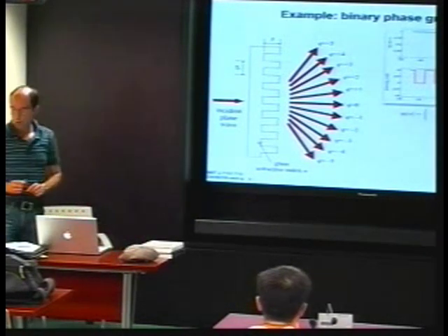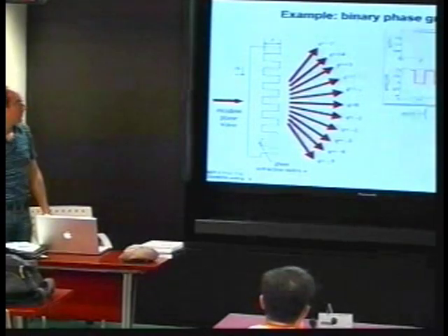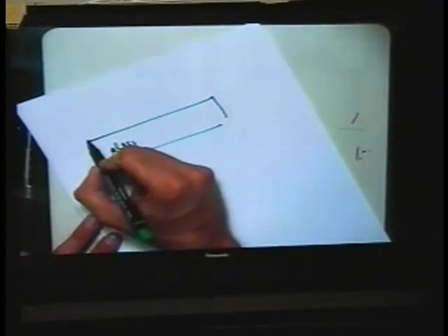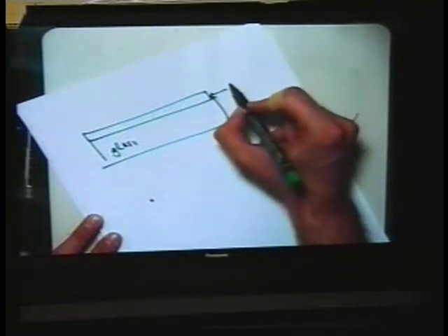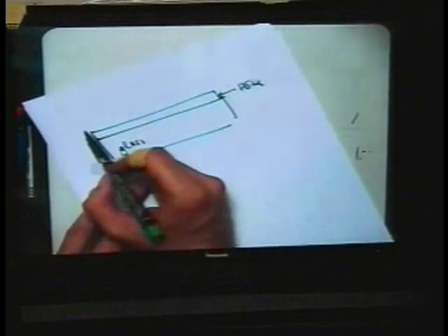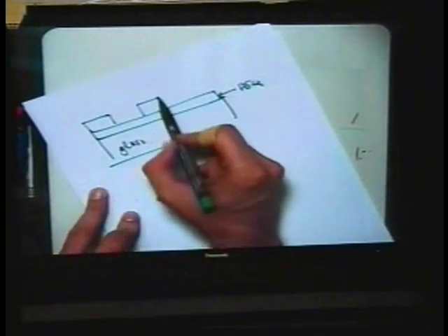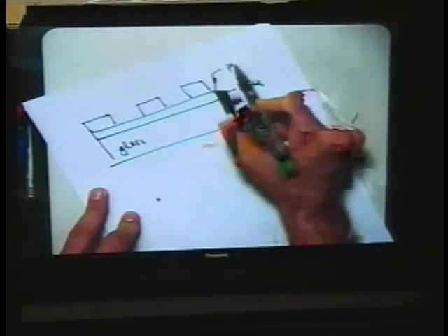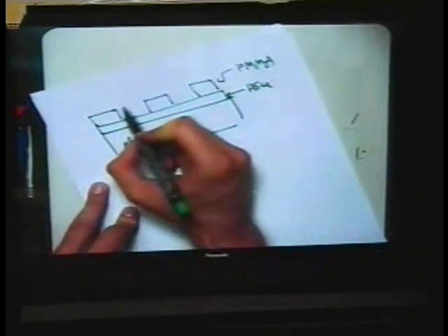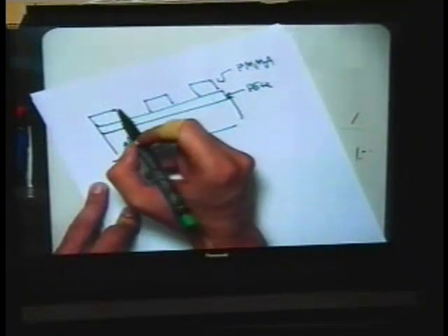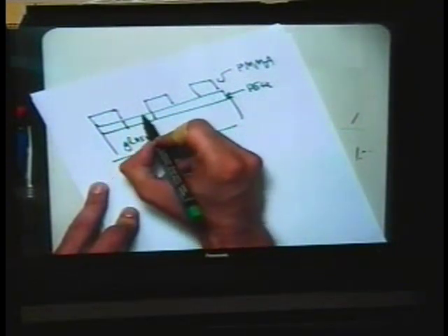So this kind of grating is also done with a similar process, but using electron beam lithography. So what you do is basically, one way to do it is you start with glass, then you coat it with a material that is called HSQ, which you can pattern using an electron beam. You put an electron beam resist on top, which is called PMMA. Then using the electron beam, you remove parts of the PMMA, and then you etch away these parts.